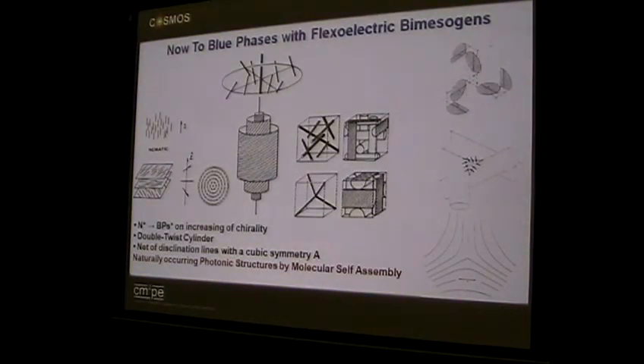Okay. Because as I mentioned, you can stabilize those particles. If you want to play games, you can play games in these systems. You can put carbon nanotubes in there, and because, if you don't treat them to make them soluble, they will try and push out of solution. So where do they go? They go to the isotropic region. Where's the isotropic region? The S equals minus a half disclination line. And so you put CNTs in there to stabilize the blue phase.